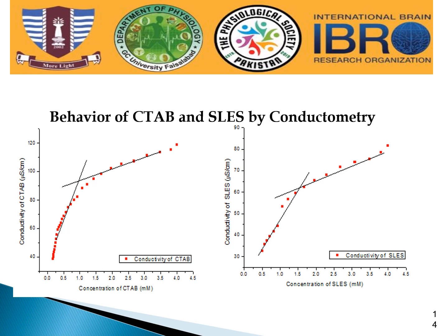We divided this graph into two sections: the pre-micelle region and the post-micelle region. In the pre-micelle region, conductivity sharply increases, whereas in the post-micelle region, the conductivity increases steadily. The explanation for the slower increase in conductivity in the post-micelle region is the binding of free ions to surfactant aggregates. Micelles are the name of these clumps of material.